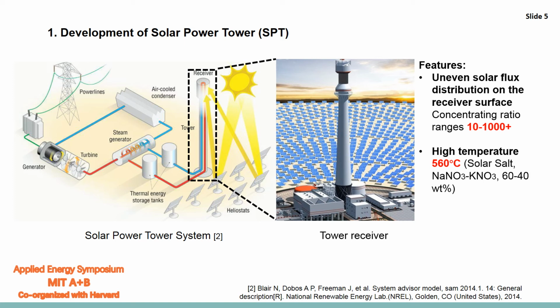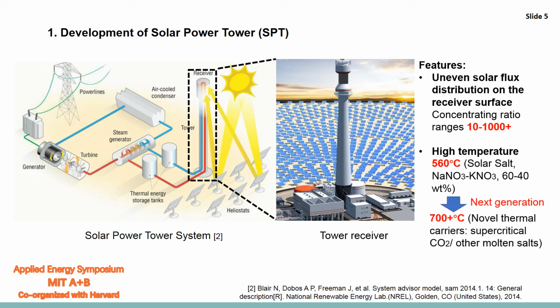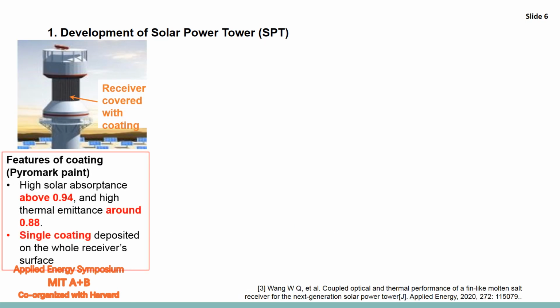The heat transfer fluid used in commercial SPT systems is generally solar salt, which can reach 560 degrees. For the next generation SPT, novel thermal carriers such as supercritical carbon dioxide or other molten salt will be used to achieve much higher temperature. To absorb solar energy as much as possible, the receiver surface is covered with one single coating. The coating in the current tower receiver is usually pyromark paint. It has high solar absorbance, about 0.94, and high thermal emittance around 0.88.